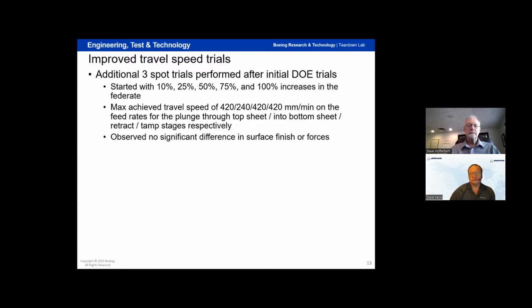And so all of these travel speeds here, 420 millimeters or 240 millimeters per minute were the feed rates for the individual plunge sections of the weld. I didn't really see any differences in the forces that were being exerted on the tool or the surface finish on the backside. If we go to the next slide,